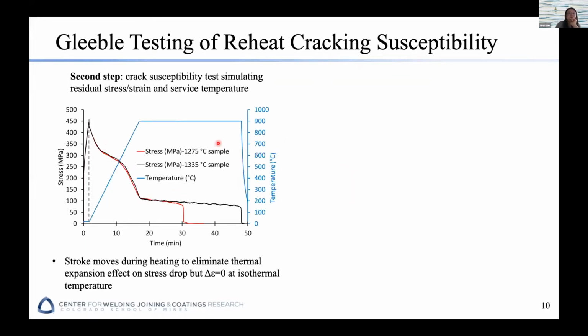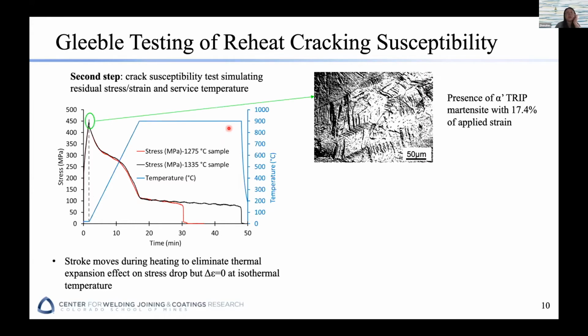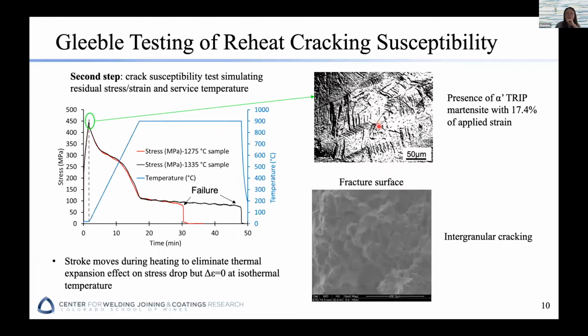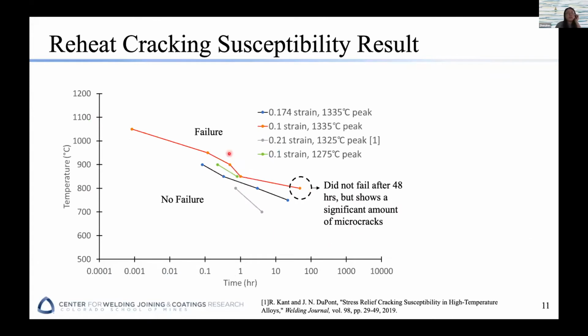Okay, and then we use the Gleeble machine, which is a thermomechanical simulation tool. So we simulate the stress and we simulate the temperature, and we want to see the susceptibility of the materials. Before the stress is applied, you can see the starting microstructure after welding. Okay, and this is the fracture surface that we see when the sample failed. We can see the intergranular cracking that shows all the grain morphologies. So this is what we got so far, the susceptibility result.